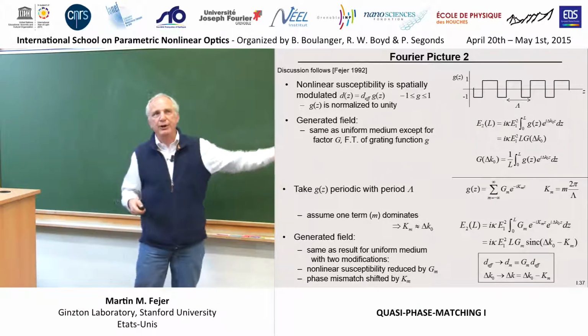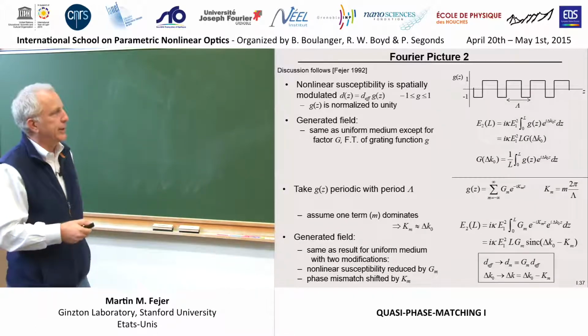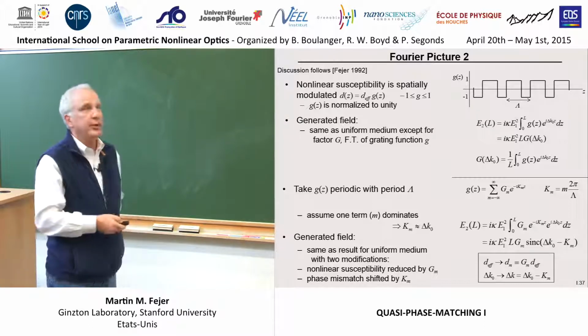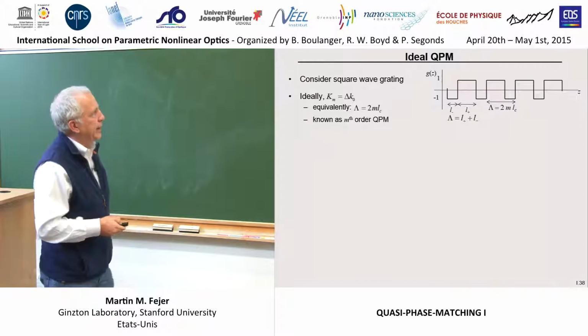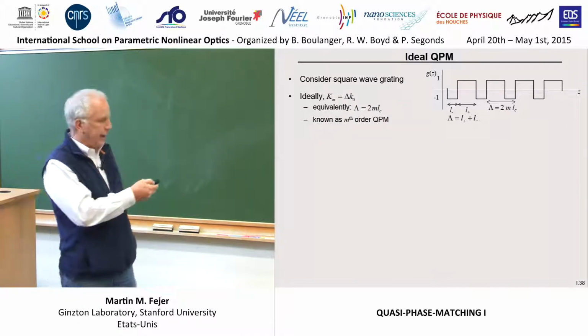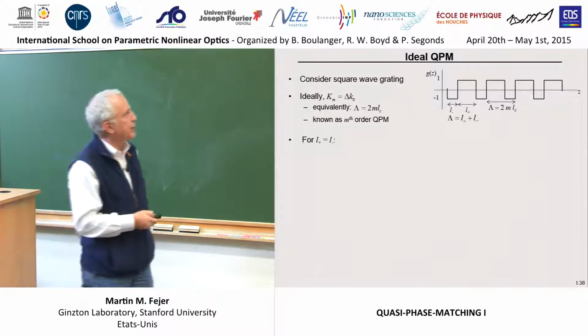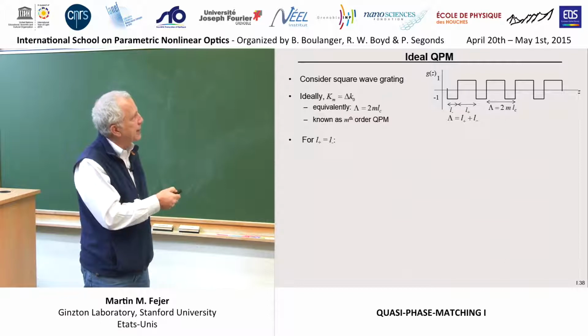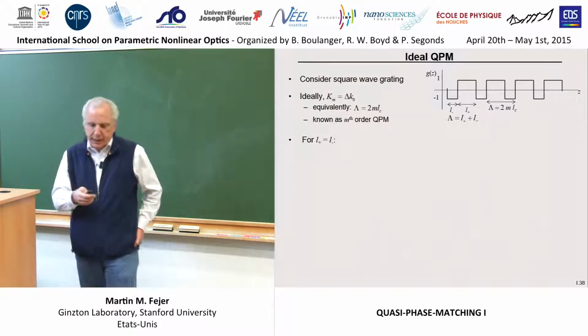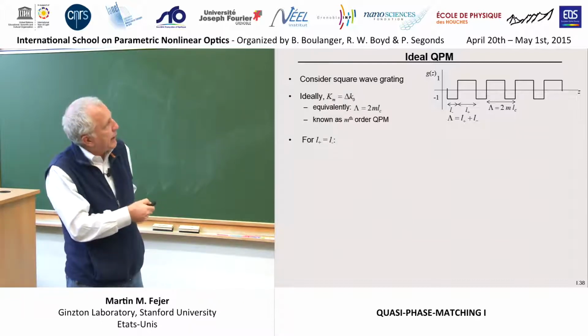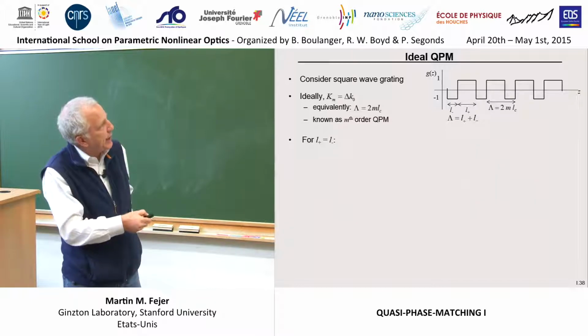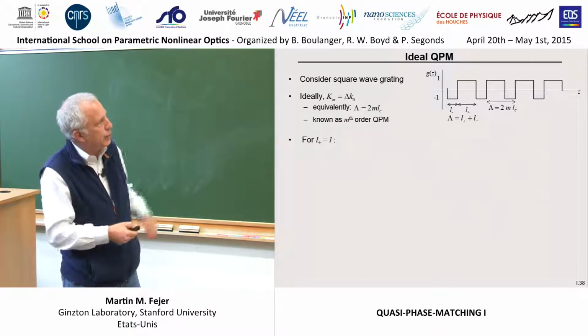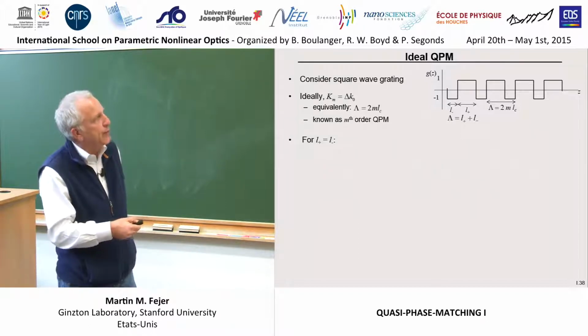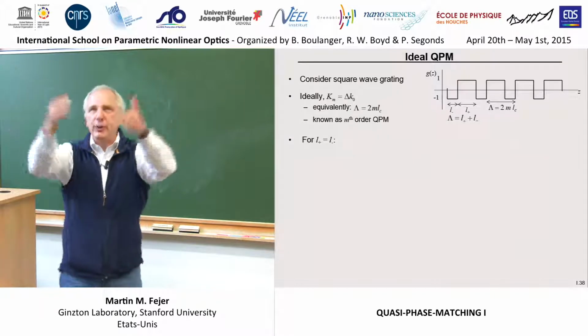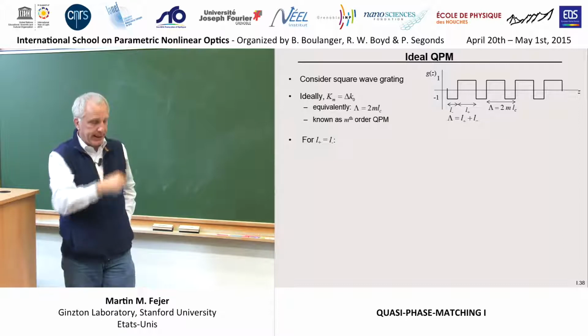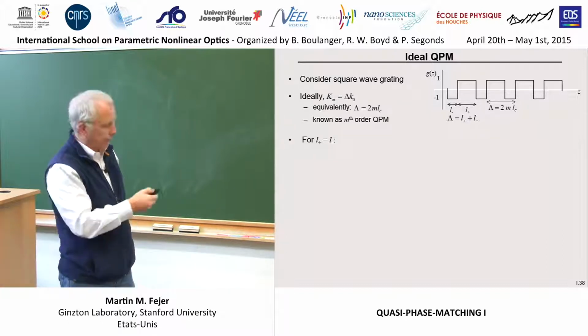Everything you know about uniform birefringently phase-matched crystals is roughly correct, or almost mathematically identically correct, for the quasi-phase-matched case with a periodic grating. So if we have an ideal choice where one of these k vectors is exactly phase-matched with our particular process, that's known as mth order quasi-phase matching if it's the mth spatial frequency component of the grating that's doing the phase matching. And in order to accomplish this, that's the same as saying the period of our grating is not equal to twice the coherence length. It's 2 times m times the coherence length. You could have a longer period grating and use one of its higher spatial frequency overtones as this higher order phase matching.